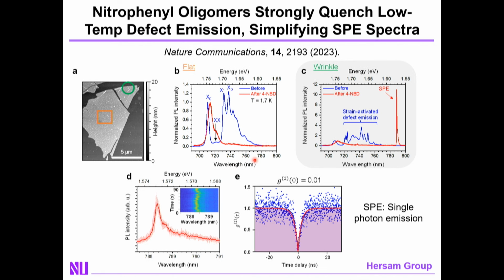What's interesting for the case of quantum information sciences, though, is the fact that if you have strain additionally present in your tungsten diselenide, which in this case is occurring from randomly occurring wrinkles that are present in the film, but these also can be induced by intentionally introducing strain, for example, via a nanopillar substrate, then what you observe is the defect spectrum becoming much more complicated, some very sharp peaks emerging. These are the single photon emitting peaks. And this is why people are interested in this material for quantum information applications.